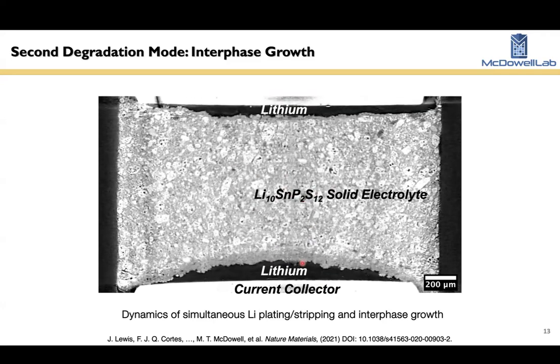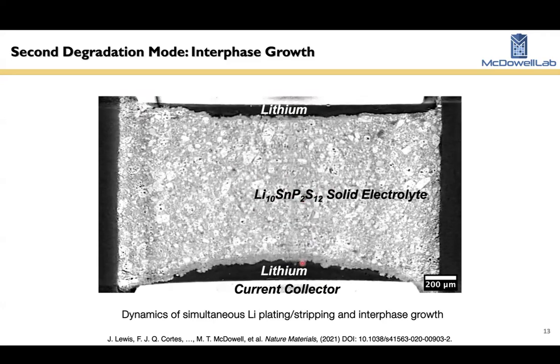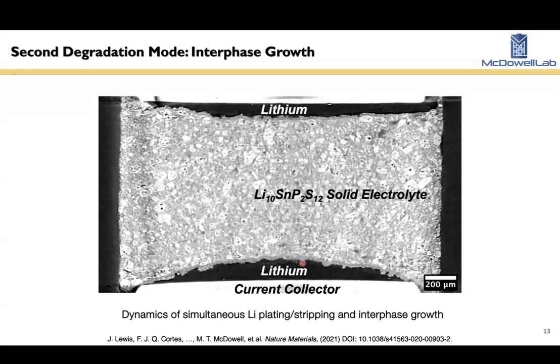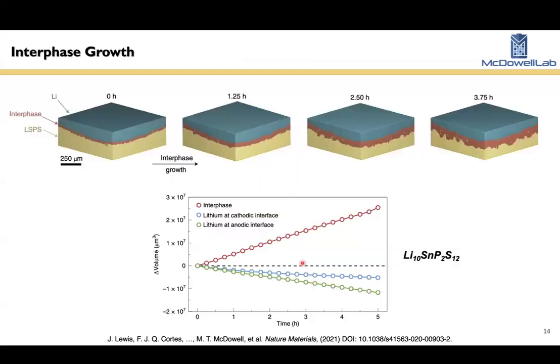But the point here is that you can quantify the growth of this phase with this sort of technique as long as it's fairly large. So we did that in this paper here, these experiments, so we can see that the interface is growing linearly with time, actually, in this case, as we're applying a current. So this represents an interface-controlled two-phase type reaction for this interface growth, which was expected.